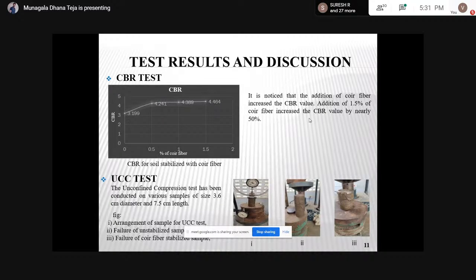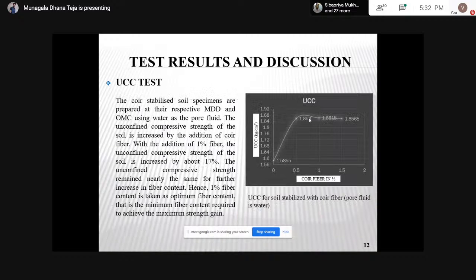In the UCS test, I took the sample size as 3.6 centimeters diameter and 7.5 centimeters length. I prepared the samples. On the right side I show the arrangement of soil samples, unstabilized soil and stabilized soil. These are the UCS test results I got at 0.5%. Compared to these results, at 1% I got a higher value. It is almost a 17% increase compared to unstabilized soil. So I took 1% as the optimal fiber content for the durability test.